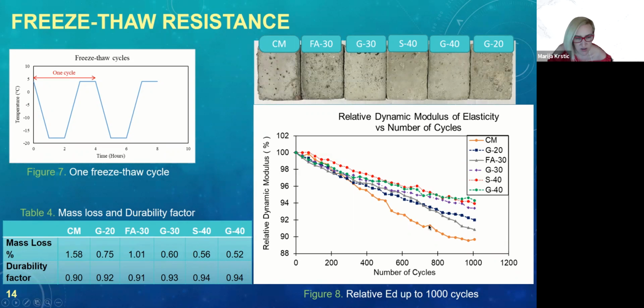Mass loss was very insignificant. Slag 40% and glass 40% had only about 0.5% of mass loss, while cement was the only one that had more than 1%. In terms of durability factor, all 6 mixtures showed that they are resistant to freeze-thaw because initially it was air-entrained concrete.